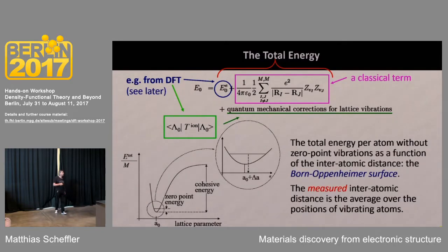And I plot this here in the following way. If you look at a typical curve, which we also will calculate in the next days, going from interatomic distances which are large to smaller and smaller ones, you're going to a minimum, and then behind the minimum, getting even closer, there's a very steep rise. This steep rise comes from a Pauli repulsion because electrons don't want to be compressed in their space, and this really is a smooth and somewhat softer function as on the left side.